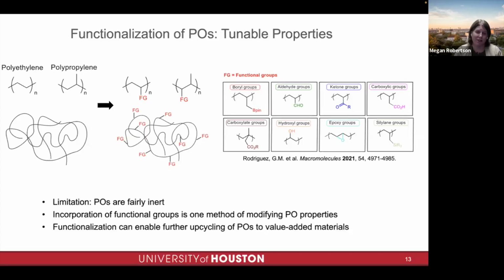So we can use these pathways that have already been established for bringing new functional groups to polyolefins, and this is all done as a post-polymerization modification, meaning this isn't something we're going to do as they're synthesized, but rather we can take the existing polyolefins and apply this type of transformation to bring something new to the material. So this is the general strategy we're going to use, where first the material is functionalized and then we convert it to our targeted material, which in our case is the thermoset polyurethane.